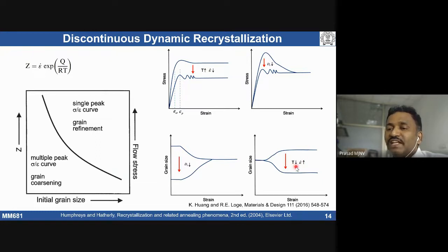When I say decreasing temperature and increasing strain rate, what is the meaning of Z? Z is basically higher. With increasing Z, we do see a grain refinement in the material. Whenever DRX happens, the grain size is going to be finer at higher Z values. For example, if you look at fine grains, there's no dependence. Finally, you're getting the same grain size here, but here the Z effect is going to be dominant. The final grains you're getting can be finer or coarser depending on the Z value.